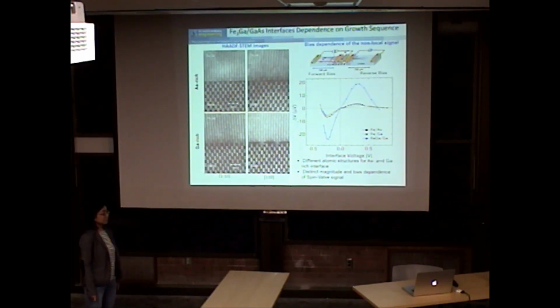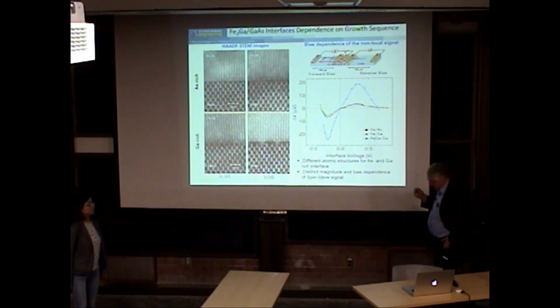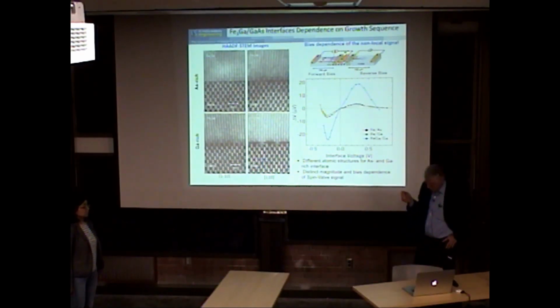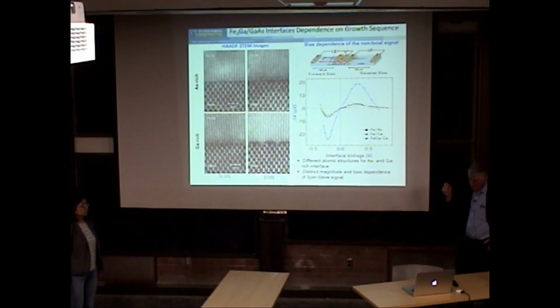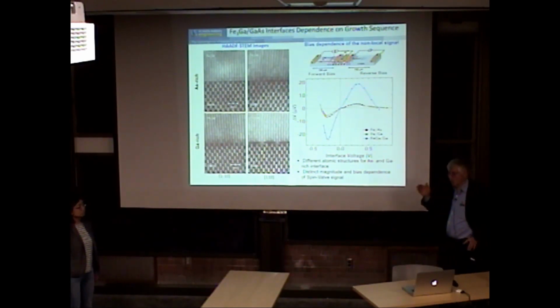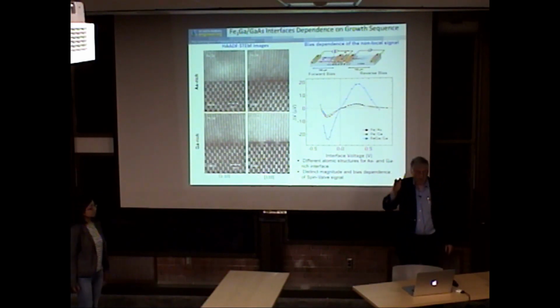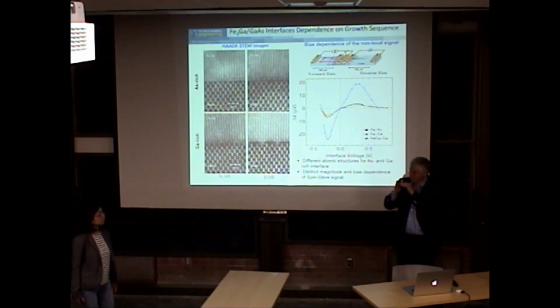And for those two materials, did you do any spin-resolved photoemission to really measure whether it is 100% or close to 100%? No, we haven't. Two groups have measured spin polarization using photoemission. Claudia Felser's group claims 93% for cobalt 2 manganese silicon. There's also work from another group in France. His measurements were very interesting: the polarization at the Fermi level was lower, and if you put something on the surface, like a little bit of MgO, it went up. The polarization was very sensitive to how close you were to the Fermi level and how you terminated it. He saw higher spin polarization just below the Fermi level than at the Fermi level.